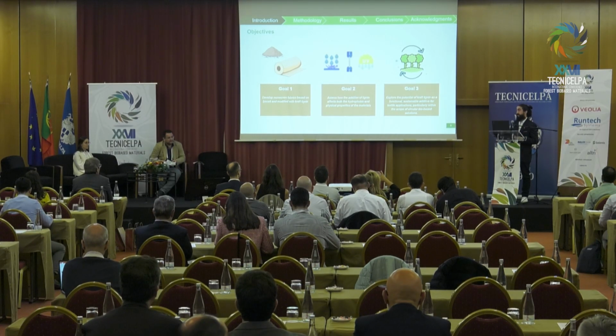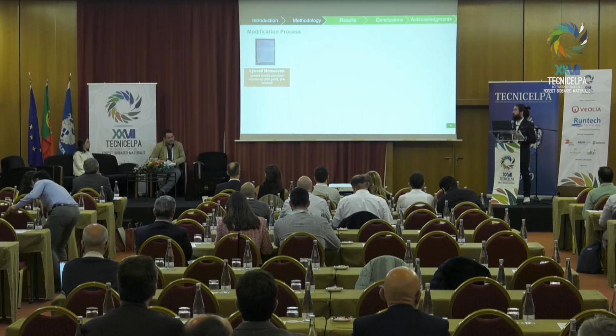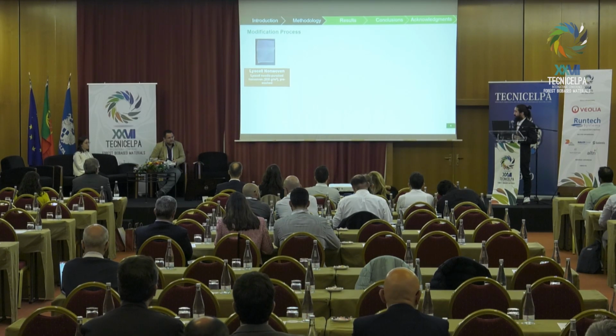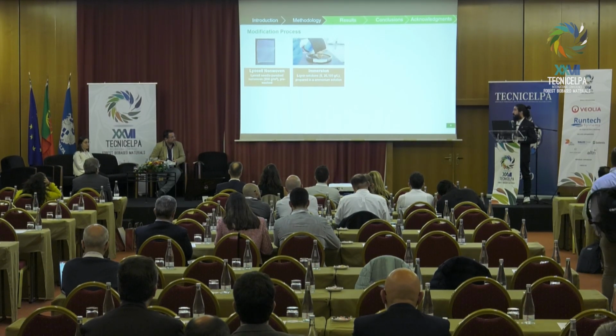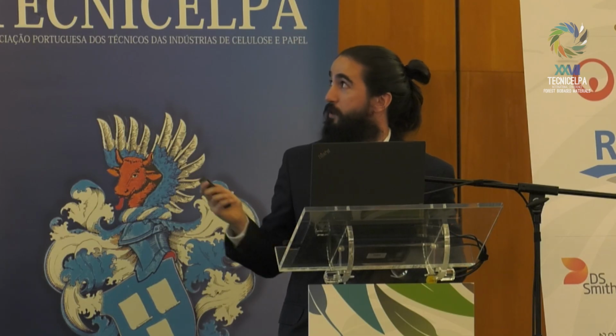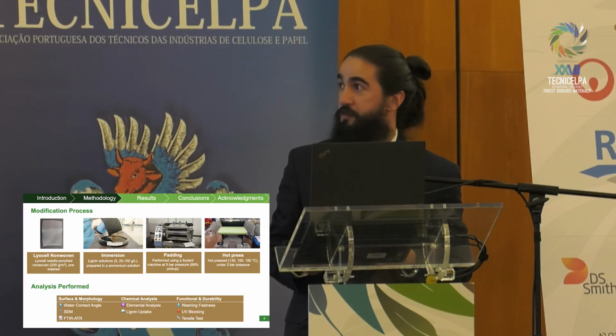So we are using a residue from a wood pulp as a resource for the textile industry. Moving on to the modification process, in our case we use needle punch nonwovens, so they are produced mechanically by entangling the fibers. And we start by impregnating them in lignin solutions that were prepared in ammonium solutions, followed by the padding in a foulard machine, which is basically two rolls that compress our sample, and then where the magic happens, which is the hot press at different temperatures.